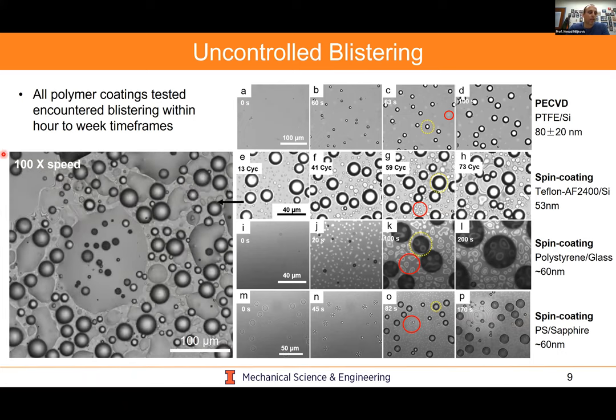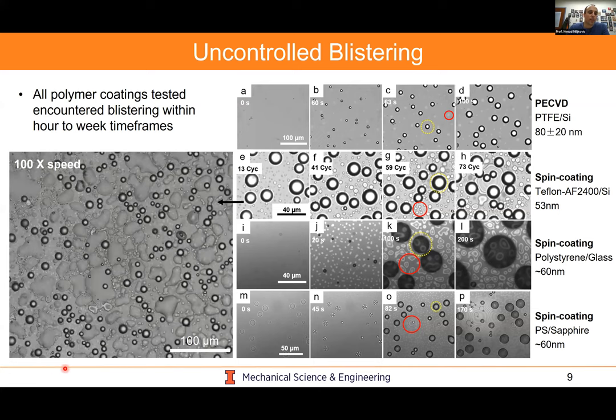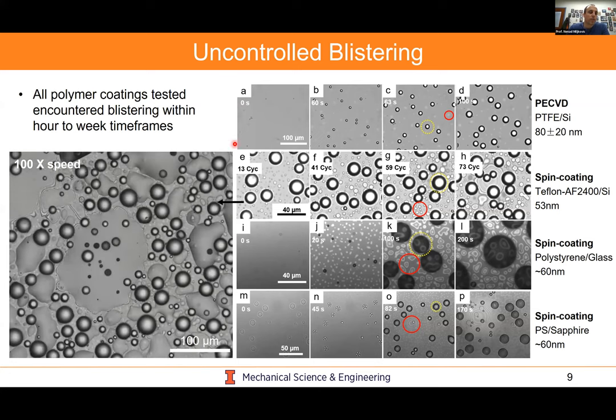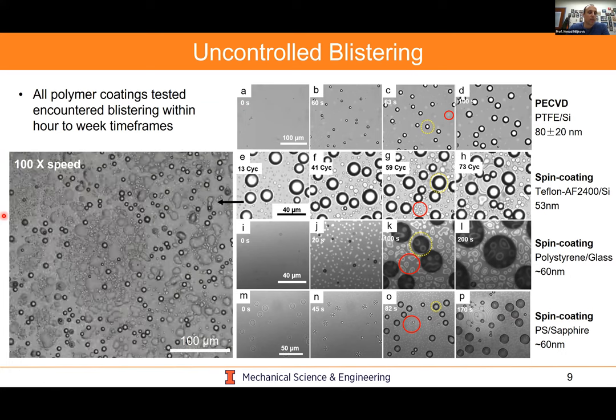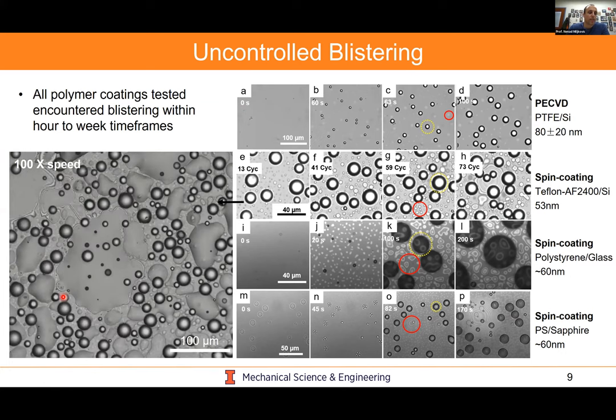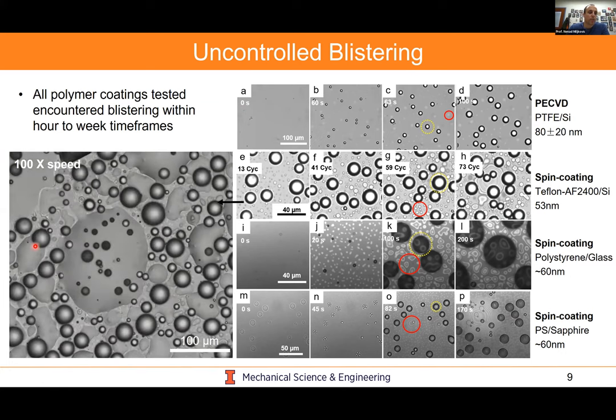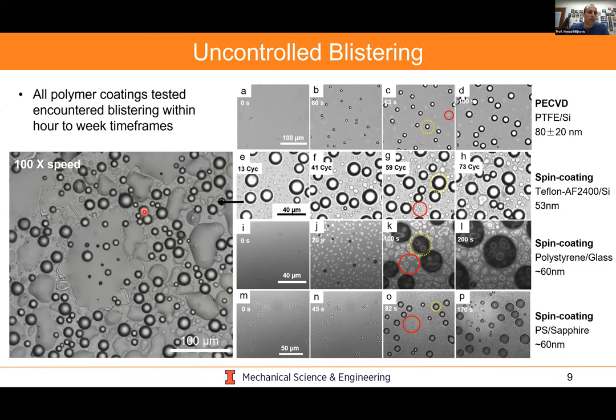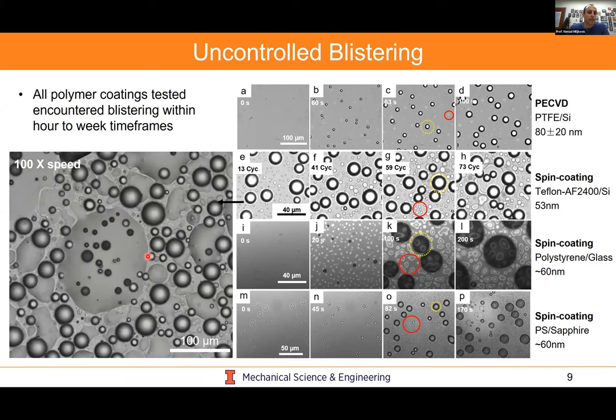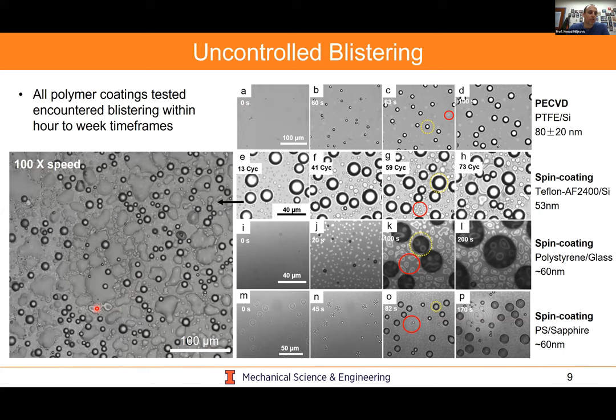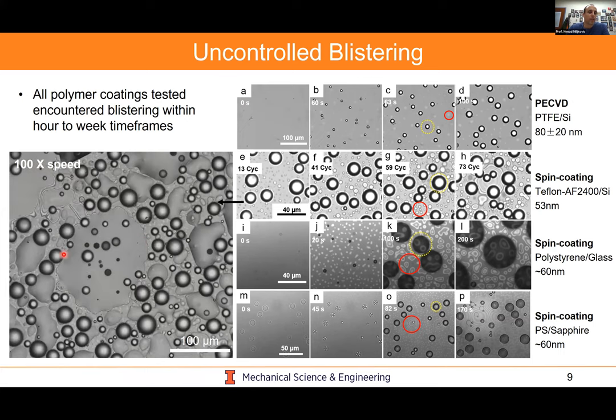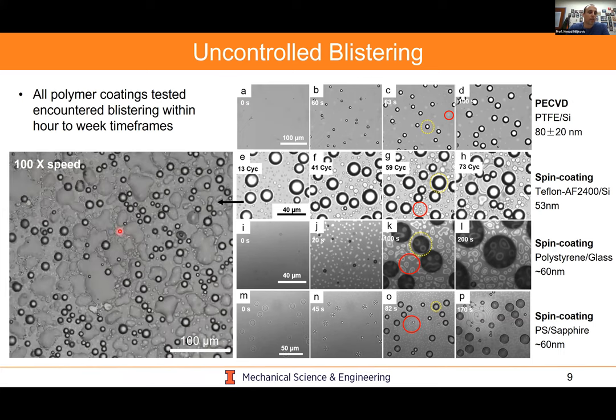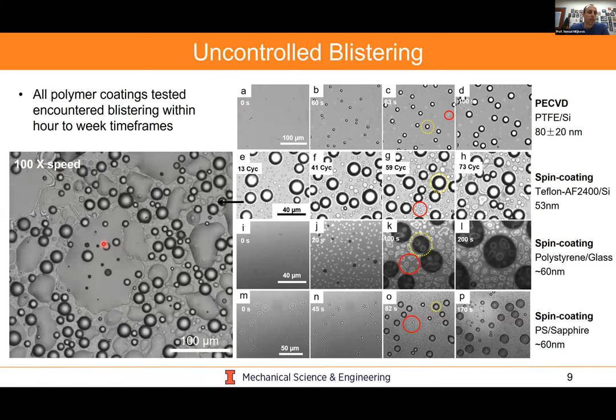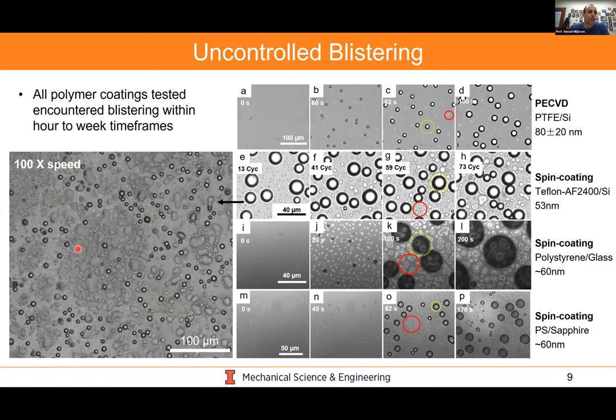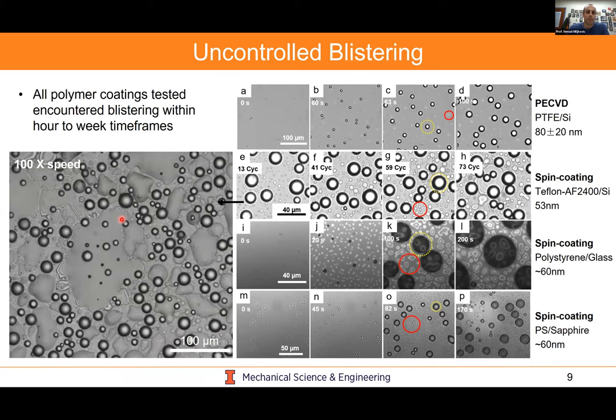The video on the left is a top view video of water condensation just from the atmosphere. From top down, what you're seeing is the substrate being cooled. These dark circles are water droplets, and these larger irregular shapes are the blisters forming. And you can see water droplets growing on top of blisters, and blisters filling up with water over time, and then slowly delaminating the film.